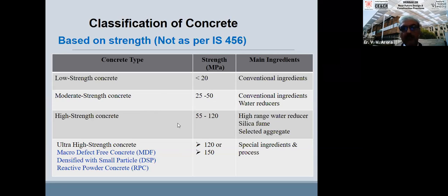The researchers are working on that. Some companies are also working on that, which can be macro defect free concrete, densified small particle concrete. Reactive powder concrete is a common name of this also. And there, aggregates are missing. That is why we call it reactive powder, because we don't use aggregates when we go beyond a certain value. The aggregate-concrete mortar interface becomes a weaker zone. So aggregates are avoided.